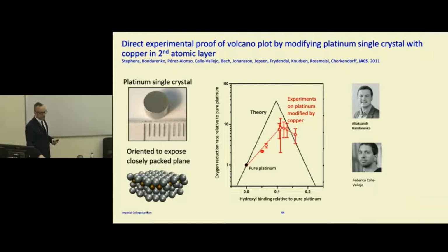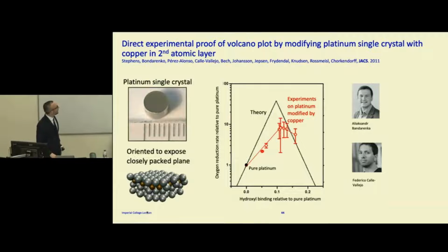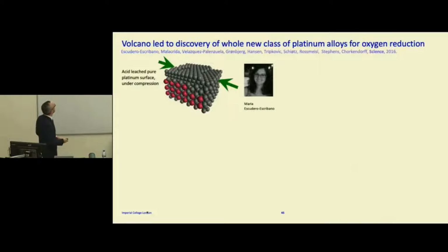We later tried to look for other new alloys, because the problem with this alloy is that you're relying on just a tiny amount of copper. That copper will leach away in the acidic environment of a fuel cell. So bulk alloys, where you have the same composition throughout the middle, would be more appropriate. Typically we were looking at alloys of platinum and rare earth metals, lanthanides more specifically. And typically what we found was that it formed a very compressed platinum structure at the surface.